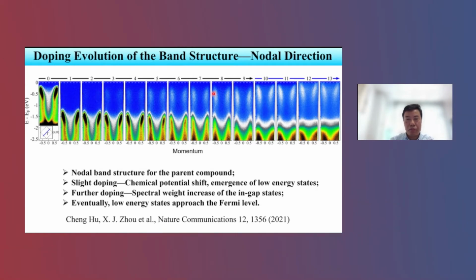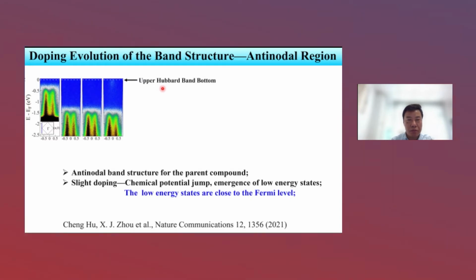On the other hand, if we look at the electron states near the (pi, 0) antinodal region, okay, this is the parent compound. In this case, its top is further away from the Fermi level, about 500 millivolts. Okay, again, if you just dope a little bit of electrons, this charge transfer band jumps down by about 1 eV.